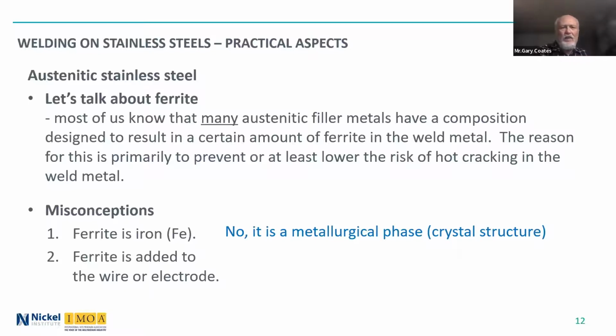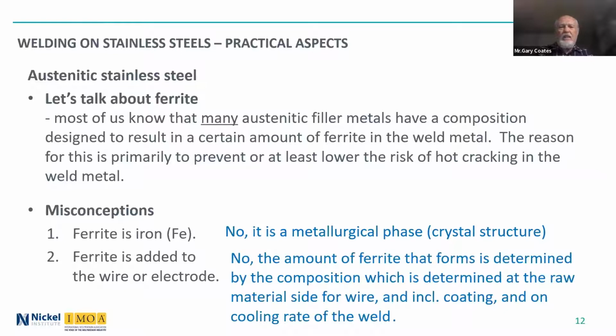And no, it is the composition that determines it, and the composition of both the wire, and if there's a flux involved, the coating on the flux. And so the amount of ferrite that forms is determined by the composition of the wire and the coating, and also involves the cooling rate of the weld. So a faster cooling weld will have a different ferrite content than one that is slowly cooled. Not a huge difference, but something that's important.